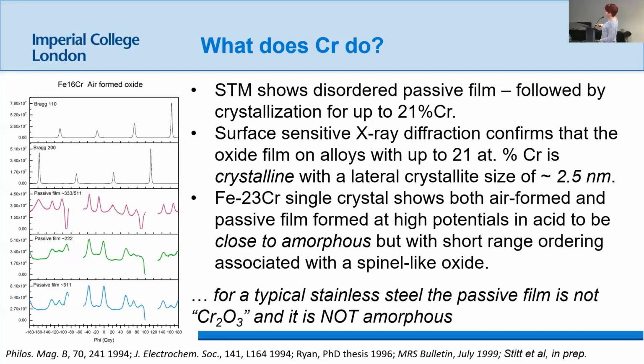So the message, and these are some very recent in situ X-ray diffraction data, which aren't showing up very clearly here, but here are the Bragg peaks for the single crystal metal, and here are peaks for the oxide film. So this is, I think, 16% chromium, but up to 21% chromium, we see these very clear diffraction peaks in situ on these oxide films and on this stainless steel. It's about 2 nanometers thick oxide under an electric field.